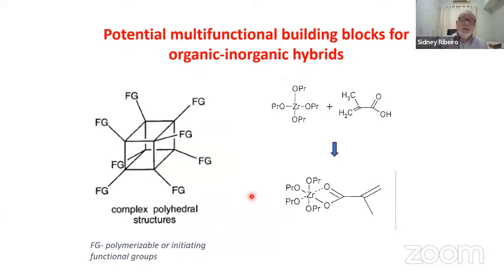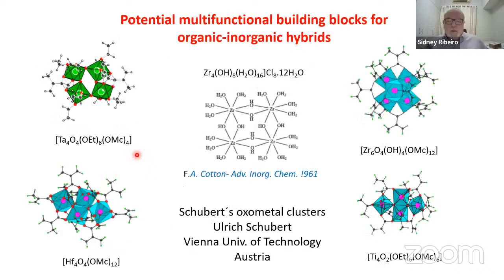So all the very active area here is in the preparation of these building blocks for the organic-inorganic hybrids. So you have here, for example, the zirconium alkoxide modified by the methacrylic acid. So what you have is an oxo cluster of zirconium atoms modified by the methacrylic acid. In general, you have this kind of structure, a metal core, and the functional groups attached to this core. This is a very nice chemistry, and we can see this in a very